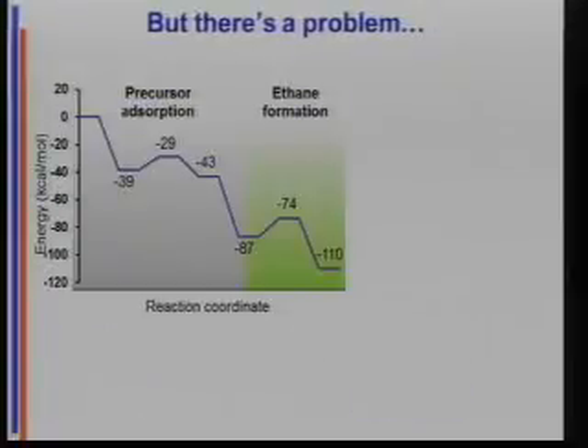And so if you look at this whole surface, here's the precursor adsorption, there's what you just saw on the other slide, here's the reductive elimination of ethane. And you look at that, what you see computationally, you think, wow, that ought to be just so spontaneously really fast at room temperature without any light. I mean, this thing ought to be going on the silver surface.